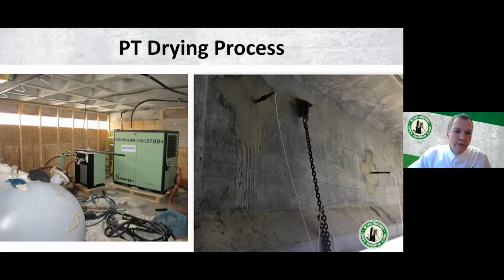If you're going to pump dry or desiccated air through the tendons, this is going to take a period of time, and from a cost-effective point of view, you're not going to do this with a bottle or a few bottles of compressed air or nitrogen. Generally, what you're going to set up on site is a dry air plant, and that is going to consist of a compressor, moisture separator, and then generally 2 types of dryers or desiccant dryers, and you're going to get the moisture content of the air or the dew point of the air down to usually around certainly -30 at a minimum, and probably around -40 dew point. Effectively, you're going to have air that's completely dry.